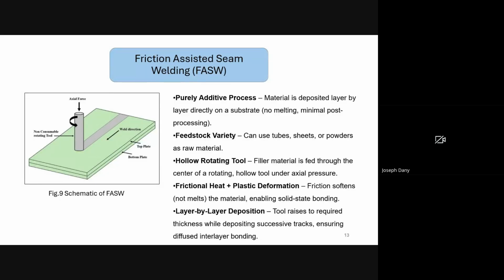The results are quite promising. FASW plates have shown higher tensile strength compared to the parent material in most of the studies. These improvements come mainly from two factors. The first one is the formation of strong metallurgical bonds between the overlapping layers, and the second one is the development of fine recrystallized grains at the weld zone.